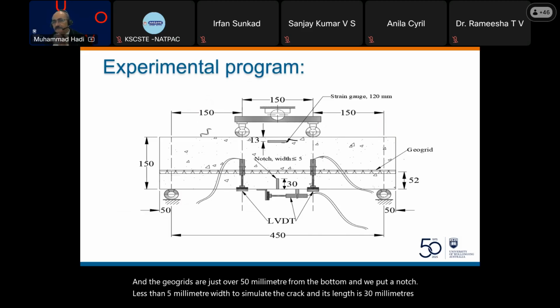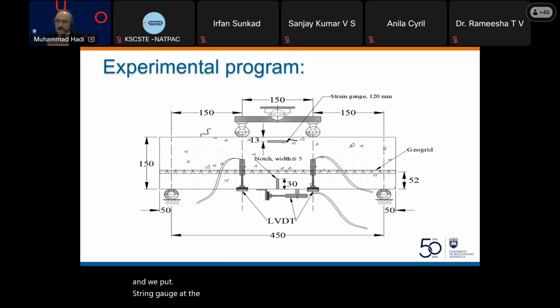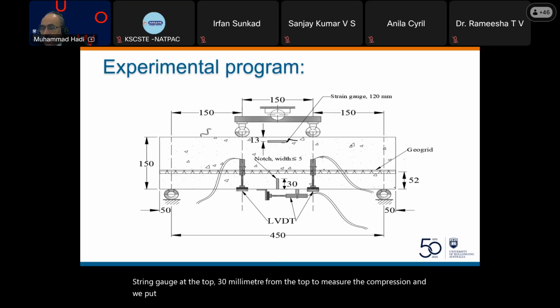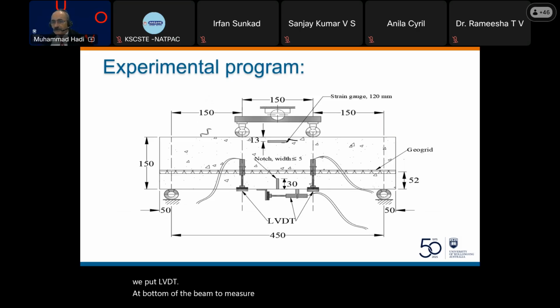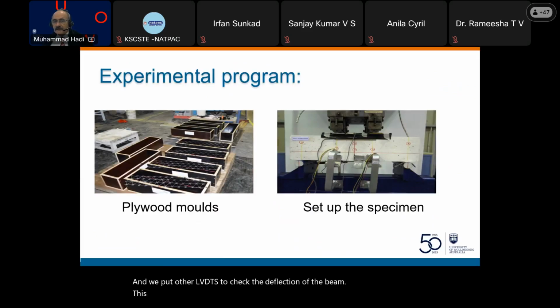And we put strain gauge at the top, 13 millimeter from the top, to measure the compression, and we put LVDT at the bottom of the beam to measure the opening of the crack. And we put other LVDTs to check the deflection of the beam. This is the formwork with the geogrids, and the one on the right-hand side, we are putting all this assembly. Again, we built all those to check the deflections, to make sure the measurements are correct.